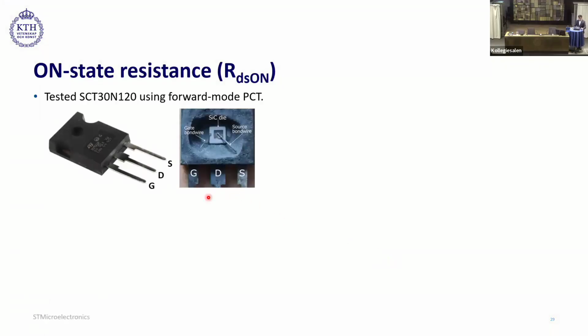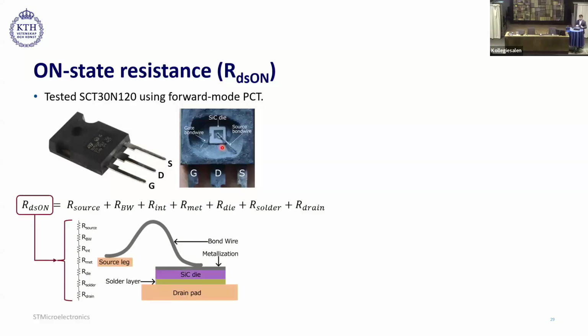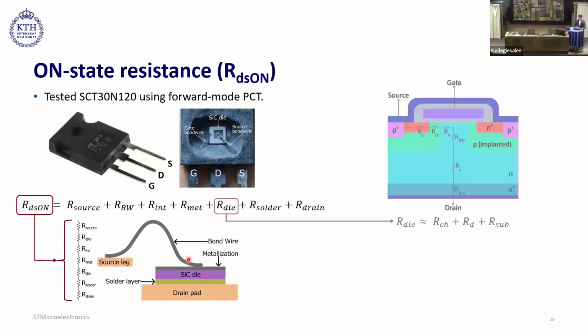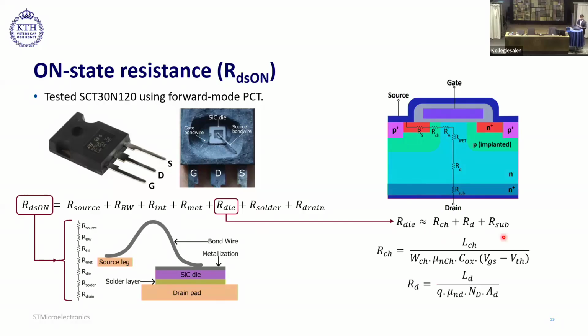So the on-state resistance, here in this contribution, we used this device with single bond wire, the SCT30N120 from ST Microelectronics. So the on-state resistance can be decomposed into several resistive components, like shown here. If you look more towards the die, then it can further be decomposed into channel resistance, drift region resistance, and substrate resistance. In literature, they say that it's mostly the channel and the drift region resistance which contributes the most towards our die. So here we have the equation of the channel resistance and drift region resistance.